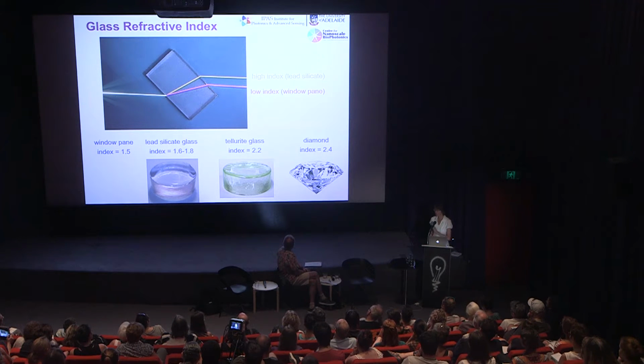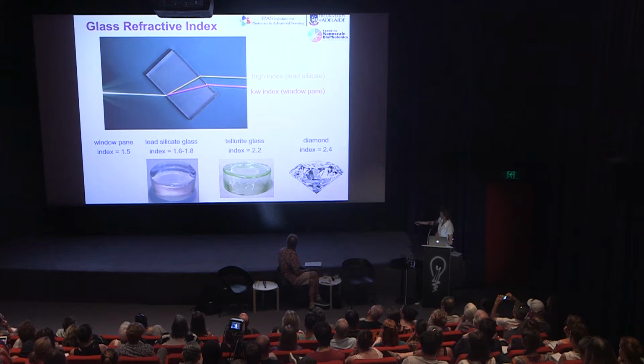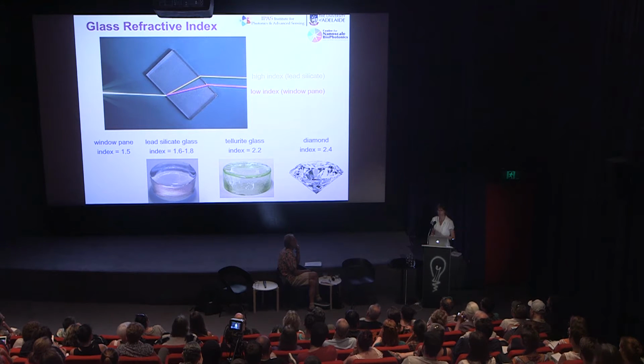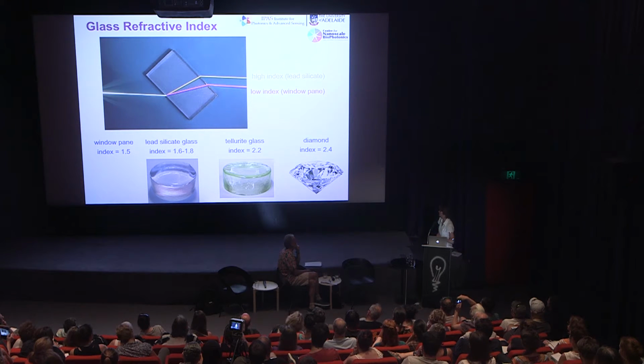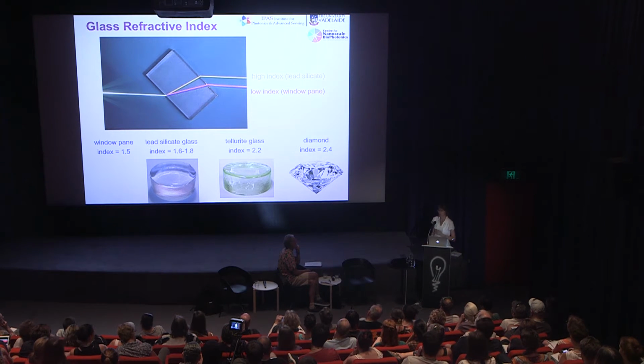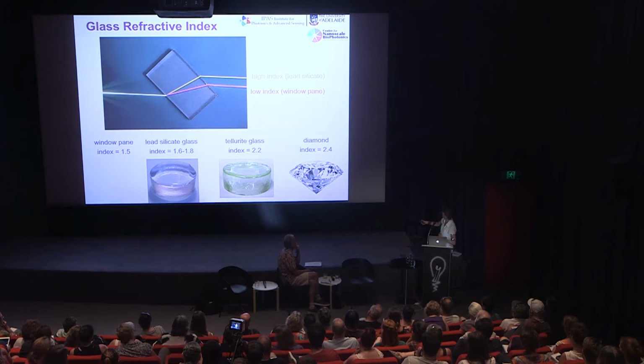Heike already gave a fantastic talk about refractive index, so I can keep it very short. I found on the internet this nice image. It's not glass, it's a polymer, but it has the same index as standard glass, showing what refraction means. What I put on top of it is the low index glass, a window pane with an index of 1.5, and we make high index glasses, or we buy commercial high index glasses, for example, lead silicate glasses. We have then a larger degree of refraction. As I said, a window pane has an index of 1.5. Commercial lead silicate glasses, we work with them quite a lot, are in the range of 1.6 to 1.8. But we also can make very high index glasses, so with the tellurite glass, one particular glass, we can achieve a refractive index of 2.2, which already comes very close to diamond with an index of 2.4.